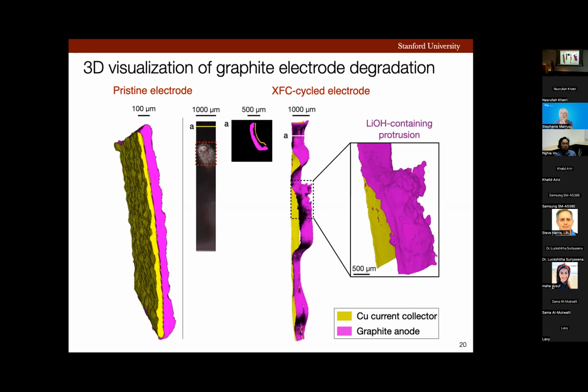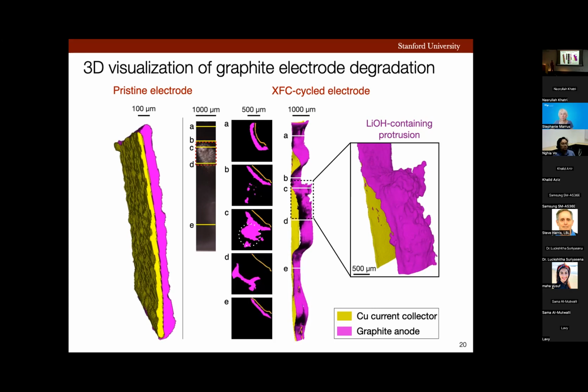For example, slice A here, which is the top view XY slice, is directly correlated to the thick yellow line labeled A and the white yellow line labeled A on either side. Same is true for slice number B. In slice C, we can see this lithium-containing protrusion very clearly, which can be directly correlated to the thick yellow line labeled C and the white line labeled C on either side. Now, if we move away from this protrusion, for example in slice E, we can see no protrusion, and we can see the graphite pretty close to the copper current collector, which can be correlated to the thick yellow and white lines labeled E on either side.